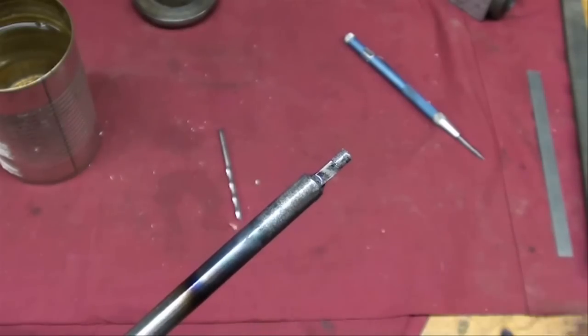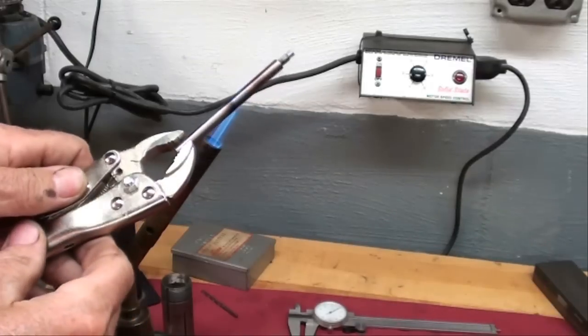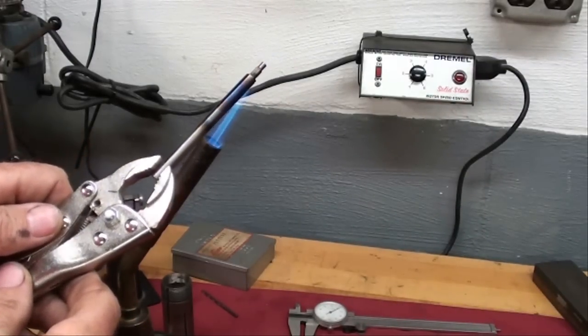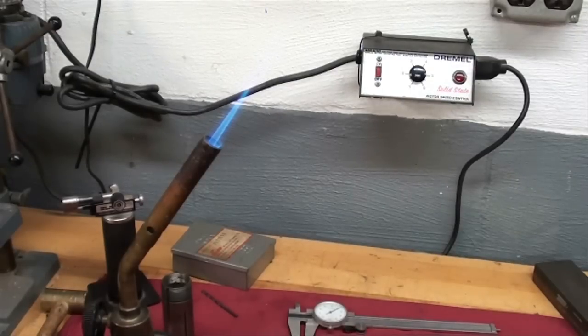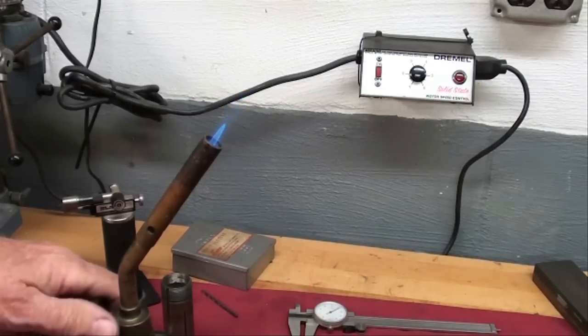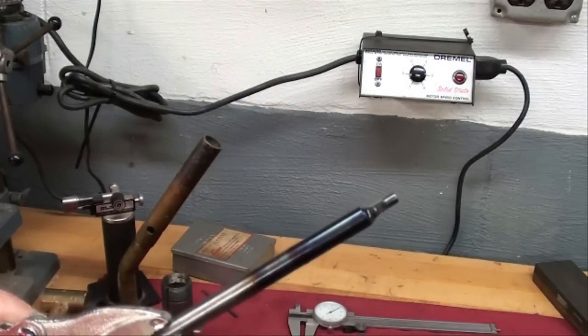But I'm going to shine it so that I can see the blue color come in. I'm not sure this will show up. Oh yeah, it's turning blue. And right at that temperature I quench it, which is around 600 degrees. See the blue color?